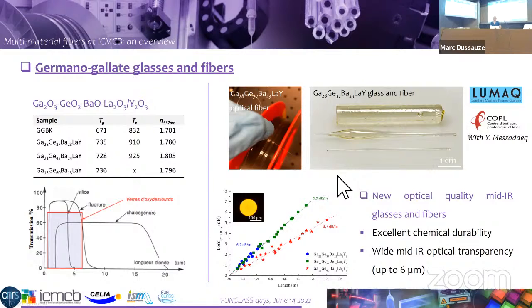So we see that the fibers were developed, and the losses are at this point quite high. As you can see, between 6 and, let's say, 3.5, 4 dB per meter. It was the beginning of the study. Now we are working, using a glove box for instance, on the purity of the precursors, on other methods, working strongly on lowering those losses.